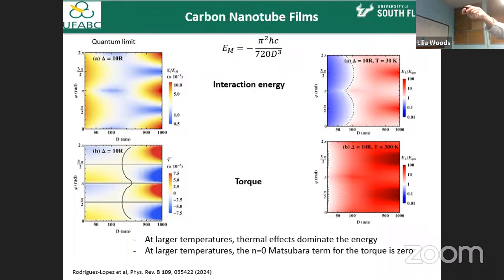In other words, the classical thermal fluctuations overtake the entire Casimir interaction. If I go to the quantum limit, which is at 0 temperature, we see these characteristic behaviors of periodicity, of the dependence of the energy as a function of relative angle, and that helps us compute the well, which is also an expected thing. One thing, however, that I noticed, and I didn't realize before, is that the Casimir energy experiences this curious separation of the thermal effect. For the interaction, the thermal effect dominates, and it always takes over the energy for temperatures that are 30 Kelvin and above.